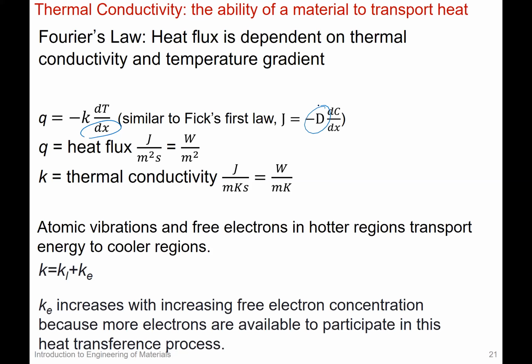At the atomic level, there are atomic vibrations, and those are the phonons. And then there are also free electrons in certain types of materials that can flow from the hotter regions to the cooler regions. So the thermal conductivity consists of both the phonon, or atomic vibration, component as well as the electronic component. For metals, the electronic component really dominates the heat flux. So K sub E increases with increasing free electron concentration, because there are more electrons available to participate in the heat transference process. This is less so for ceramics. There aren't as many free electrons, so it's really dominated by atomic vibrations, or phonons. But of course, that's not as big a part as K sub E.